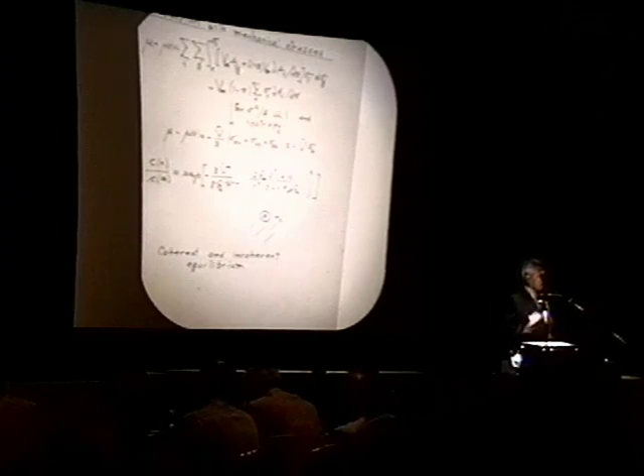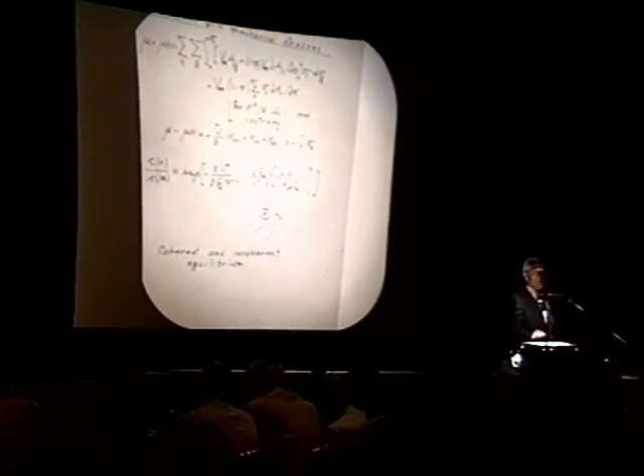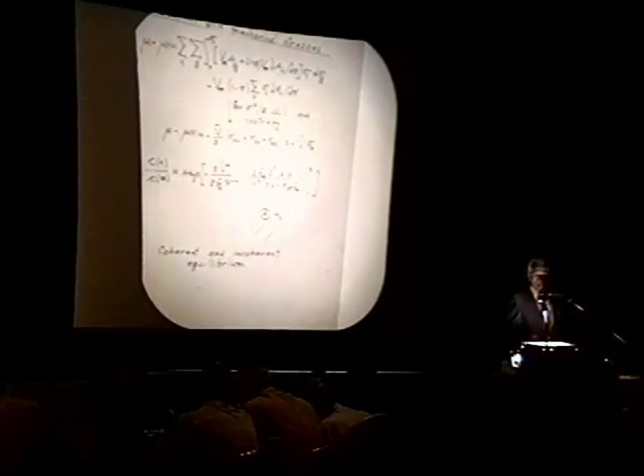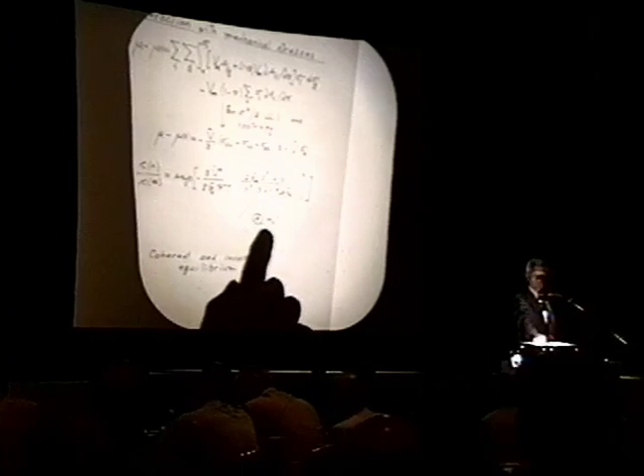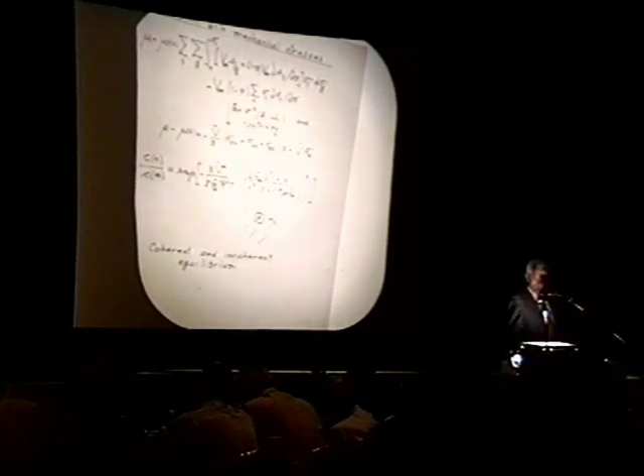That develops a different concentration distribution, therefore a different phase diagram. The coherent phase diagram is really thermodynamic, but it's a metastable, higher energy, higher free energy situation. To go from coherency to incoherency, one has to have nucleation of dislocations, which can happen only when the beta has grown sufficiently large so as to be able to pay for the energy creation of dislocations by the energy diminution of going from coherency to incoherency.